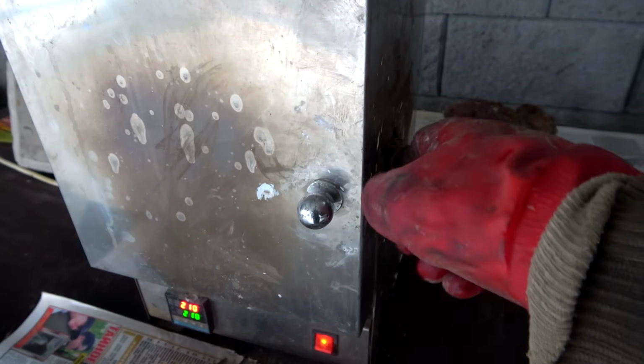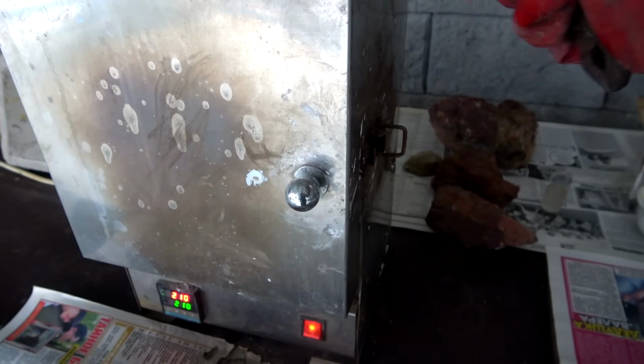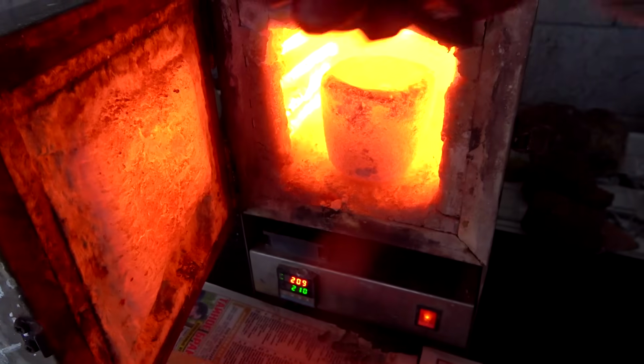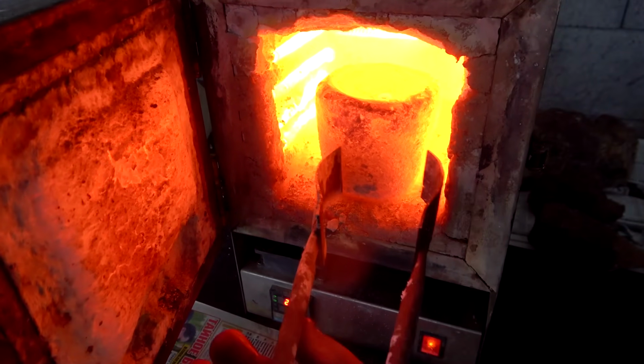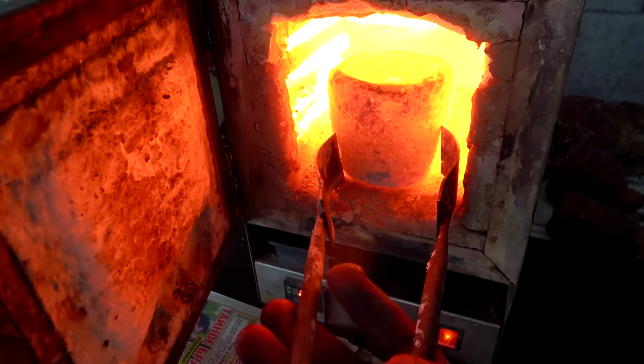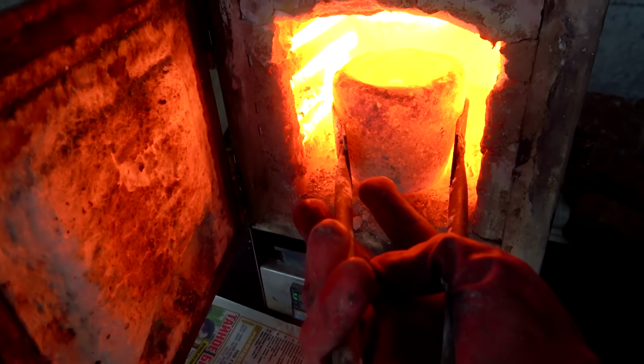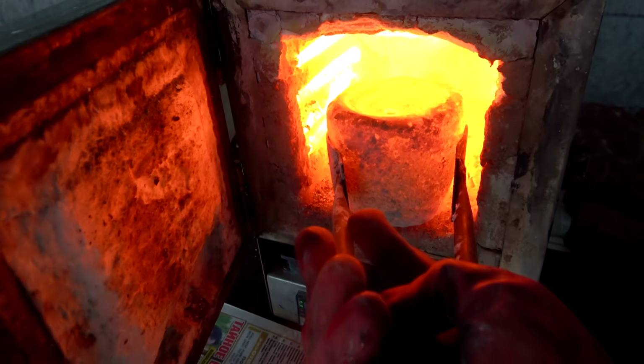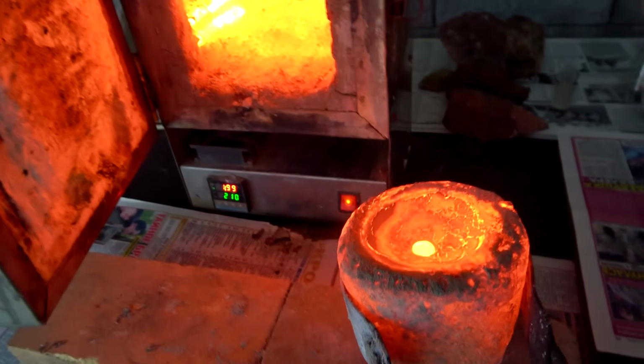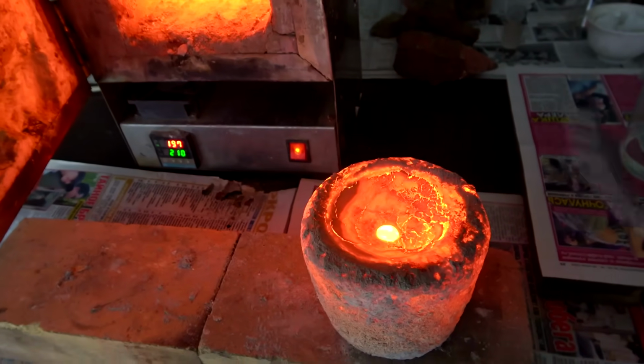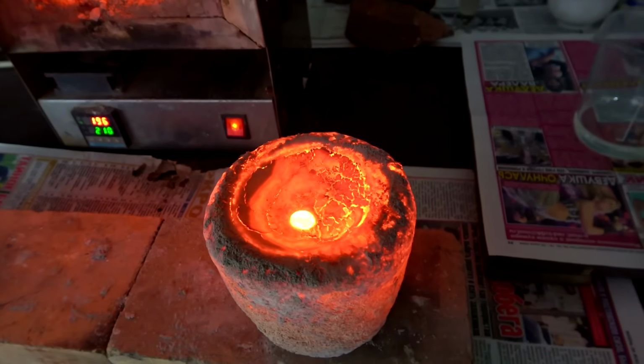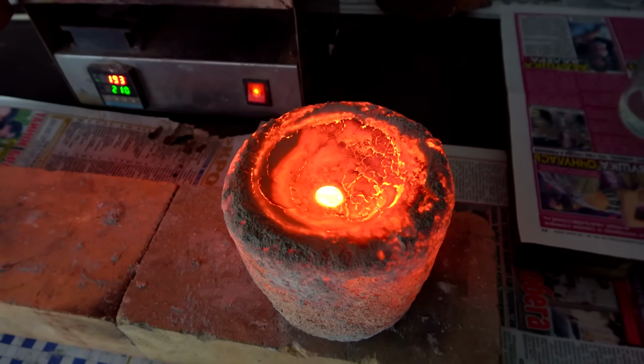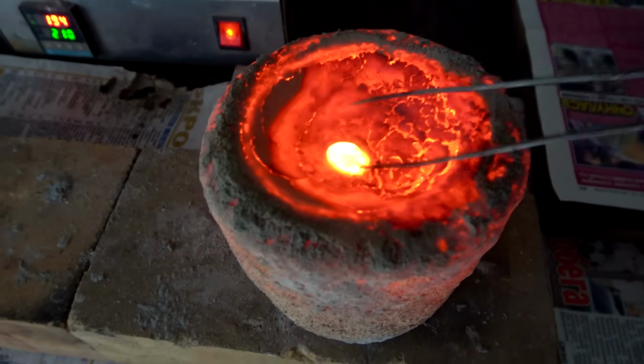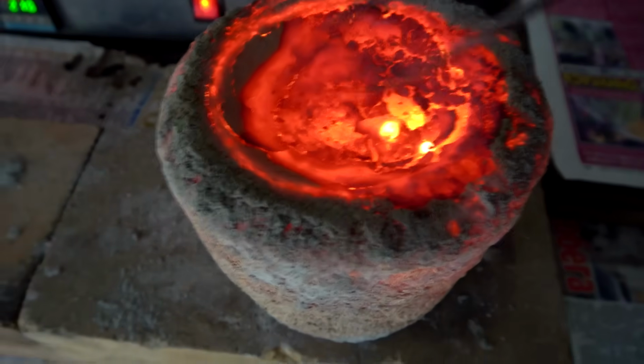And now, dear viewers, the long-awaited moment has come to find out how much gold I managed to extract from this batch of ore. I take out the crucible and see that cracks have formed and gold has seeped into them. First, I carefully remove the untouched gold bar, and while the mold is hot, I remove the remaining gold balls that have leaked into the cracks.